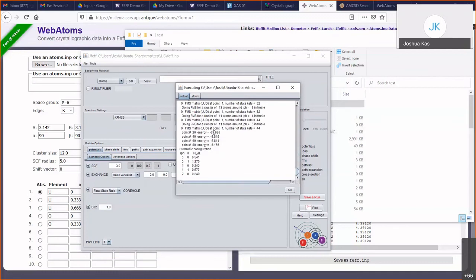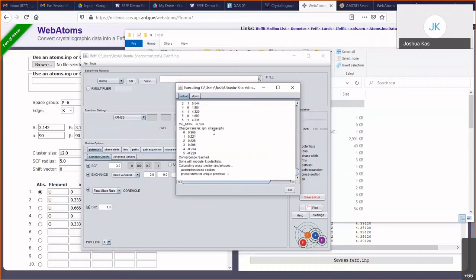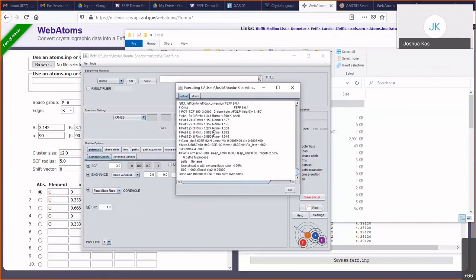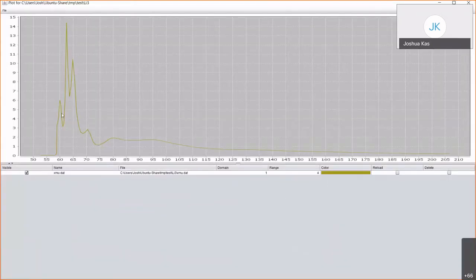So you can see that because the absorption of the Li1 and Li2 are nearly identical, probably the densities around them are nearly identical as well, or at least the spherical densities, which is what we use. And so you could probably get away with only having one potential for those two lithium types. And then, well, we'll see if this one's different. Okay, so now let's plot this one. Okay, clearly this one is different than the other one. Okay, so let's open up the other one again.